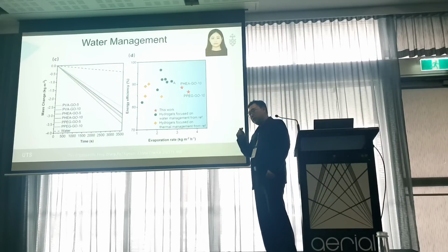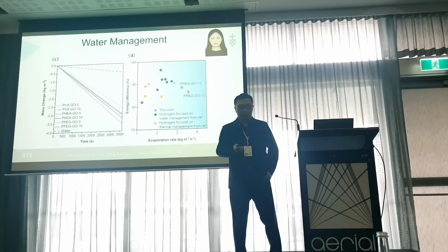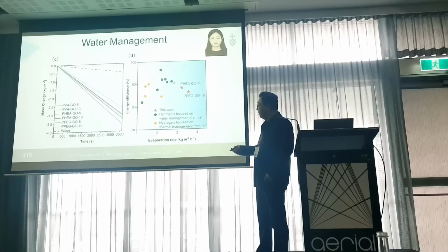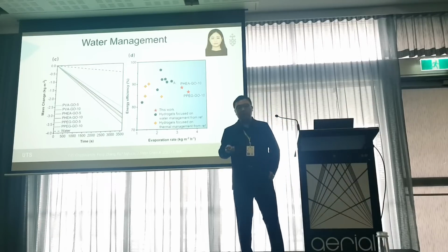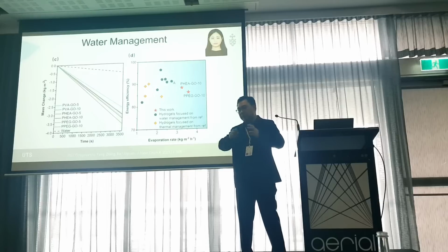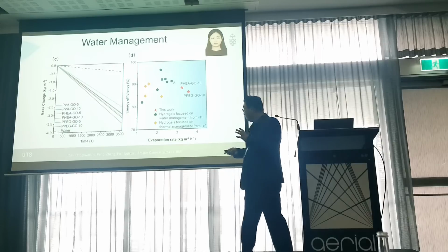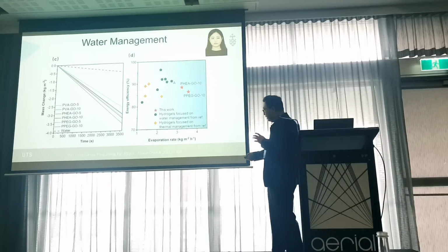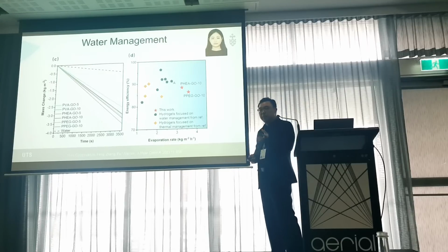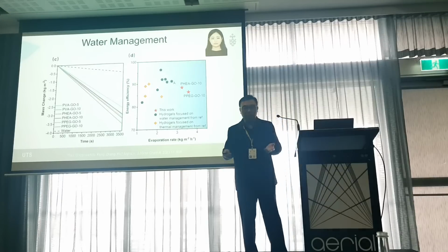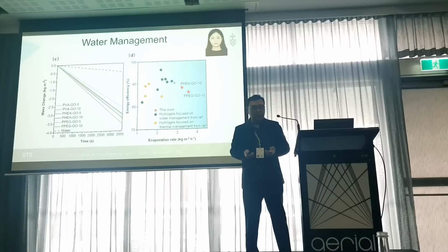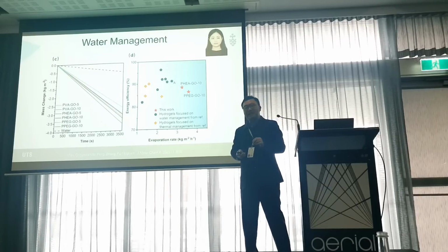Yeah, they achieve 3.6 kilogram per square meter per hour. And this value is definitely higher than the PVA one. PVA with 10% here is about 2.8 kilogram per square meter per hour. So it demonstrates that the rapid water transport definitely affects the SVG performance. And this work was conducted in 2022. So at that time, we found that 3.6 was the highest value compared to all the conventional and 2D hydrogel systems. But the last study we conducted this year, we break this record.